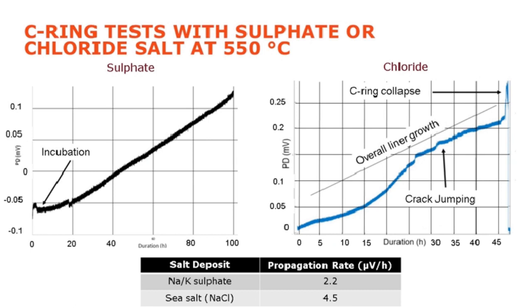If we have a look at what we've got here, these are PD plots. These represent the crack growth or propagation rate throughout the test. The way we do this is quite a common technique used in fatigue, less so in stress corrosion cracking, and less so at high temperature with deposit-induced corrosion. But it's quite a useful method for us to look in a bit more detail at what's going on. What we do is pass a large current through the specimen, and we have a couple of probes either side of where we expect cracking to occur. As that crack propagates and we lose specimen cross-sectional area, we see an increase in potential drop or resistance, which we can measure, and that corresponds to our crack size. So there's two tests here.